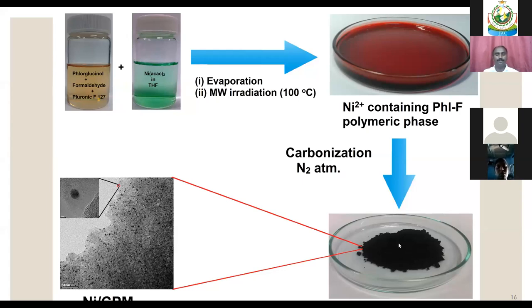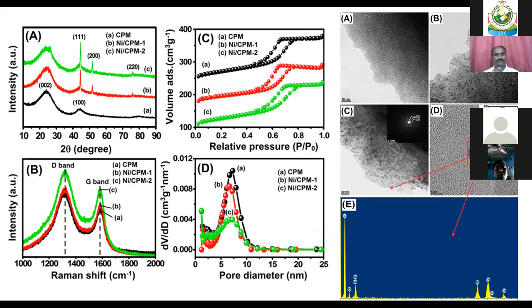So this porous carbon material contains nickel 2 plus and nickel 0 atoms. You can see the TEM image of the nickel-containing porous carbon material. You can see the single black dots, which indicate the nickel. So after the chemical preparation, we get the porous carbon material and characterize it using XRD, BET surface area, Raman and TEM images.